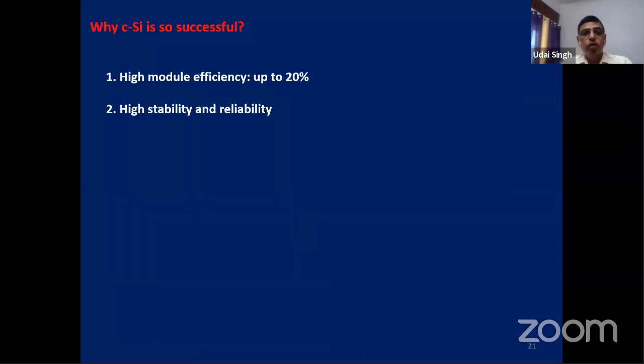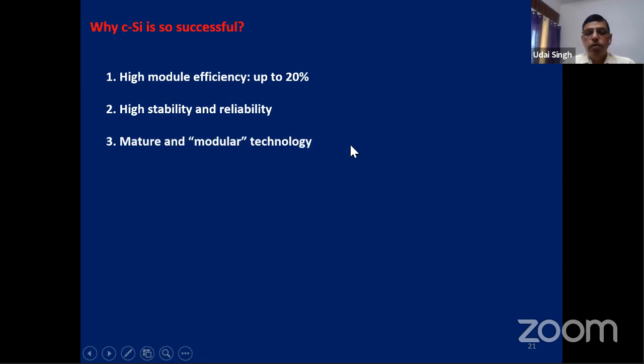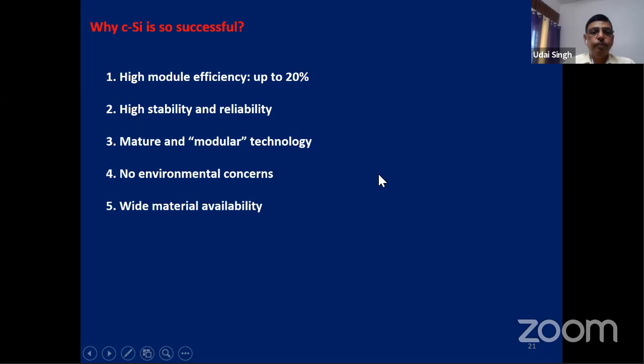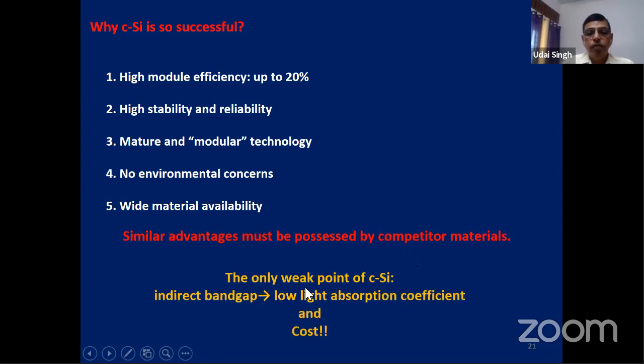So why is crystalline silicon so successful? Because it has high module efficiency, around 20%. It has high stability and reliability. It is a mature and modular technology, and it has been researched a lot. If you want to set up a plant, the next day you can buy a ready-made plant and start production within 6 months. No environmental concern, and raw material is widely available. The silicon you get from sand. So when you are looking for some other material, you have to look for similar advantages. Otherwise, it is not going to be as successful. The only weak point for silicon was that it is an indirect band gap, so the light absorption coefficient is slightly low, and the cost. But for the last 1 or 2 years, the cost has come down drastically.